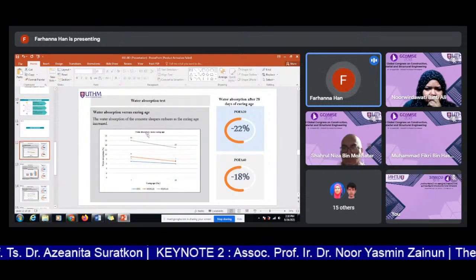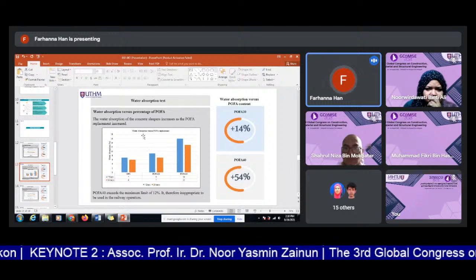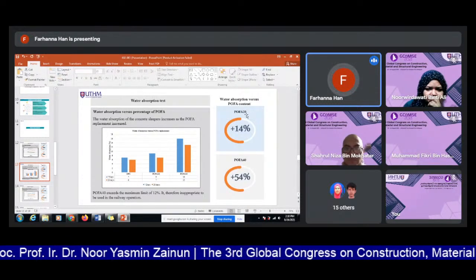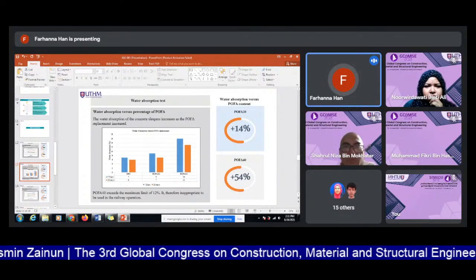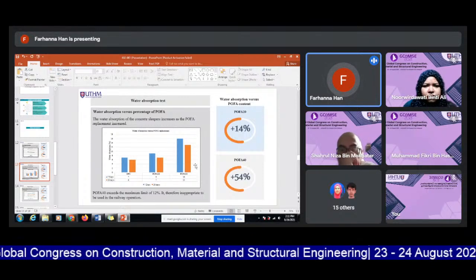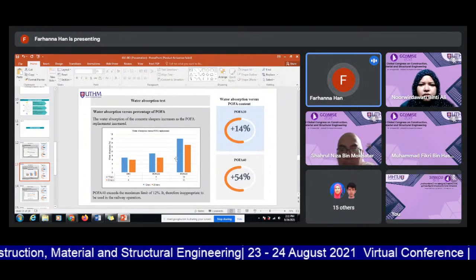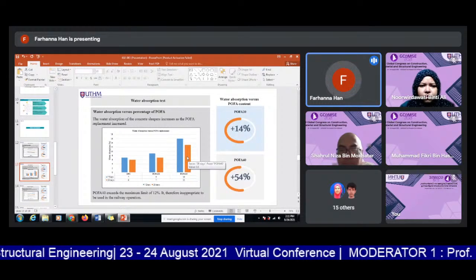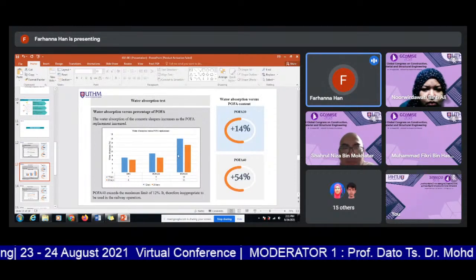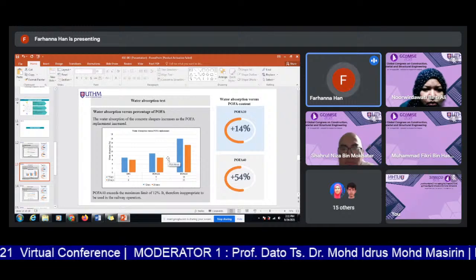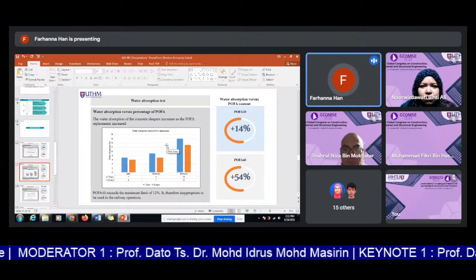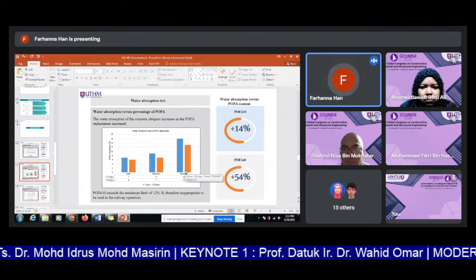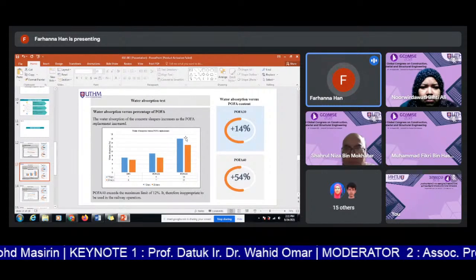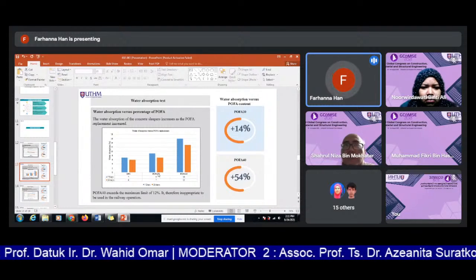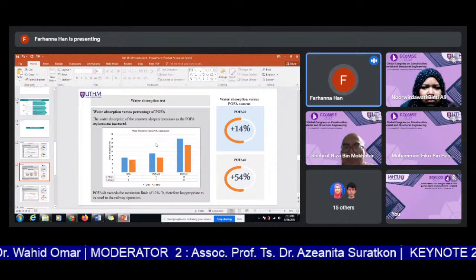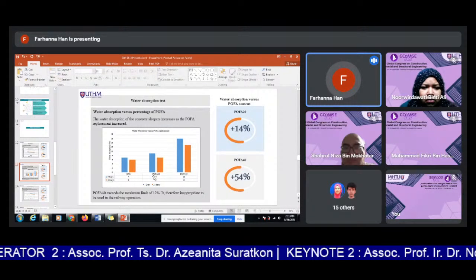Although the water absorption reduced with curing age, as the percentage of POFA increases, the water absorption also increases. As you can see, for 20% of POFA, the water absorption increased about 14%. And for POFA 40, the water absorption increased by 54%. This may be due to the use of untreated POFA, which contains a higher amount of carbon and larger particles, which tend to absorb more water. According to the British Standard, the maximum limit for water absorption is 12%. Since POFA 40 recorded a water absorption of 13%, POFA 40 cannot be used in the railway operation. But POFA 20 recorded a water absorption of 7%, so the optimum POFA content that can fulfill the water absorption requirement is 20%.